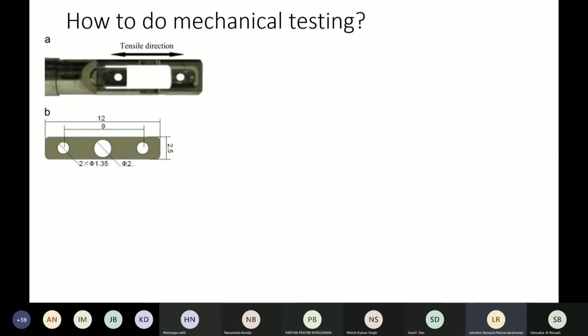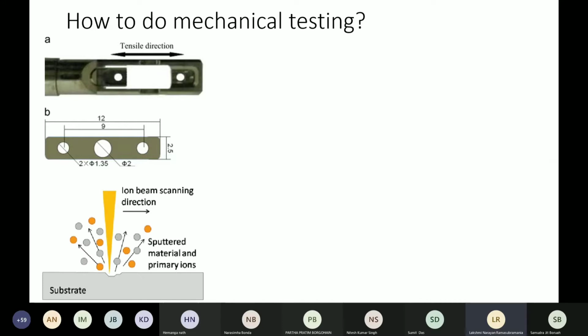So now we are going to do mechanical testing inside the TEM. That is how we are going to do it, because we have to observe the stress and strain. We have to observe what happens inside the material. That is the purpose. There are several companies which have now developed sample holders in this fashion, where you keep the sample on the right hand side of this holder, and on the left hand side, there is a movable screw. This movable screw can move in the tensile direction as depicted here. And we are going to use something called focused ion beam, where gallium ions are pumped onto a surface and these cut through the material and give you the desired shape.